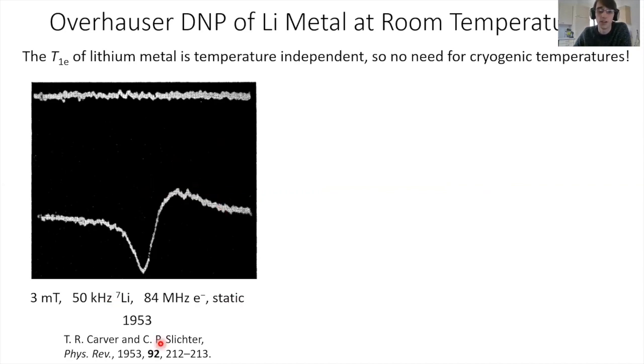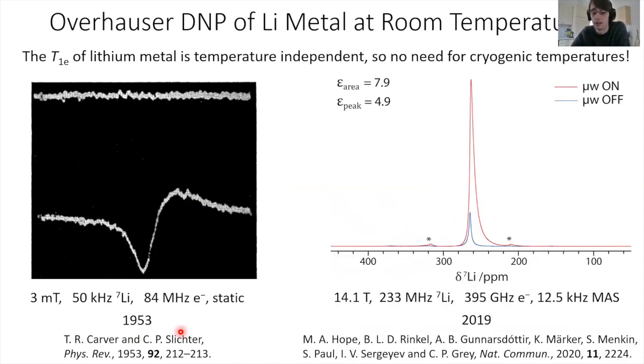Okay, so this is what we could do in 1953. And you can see in 2019, we've got much better at making figures. We've also made some other progress. This is now at 14 Tesla, so that puts our electrons at 395 gigahertz. And this is only possible now with the gyrotron technology, which has been developed. You see we have much higher resolution. These are also performed under magic angle spinning conditions, 12.5 kilohertz. But again, this is at room temperature.